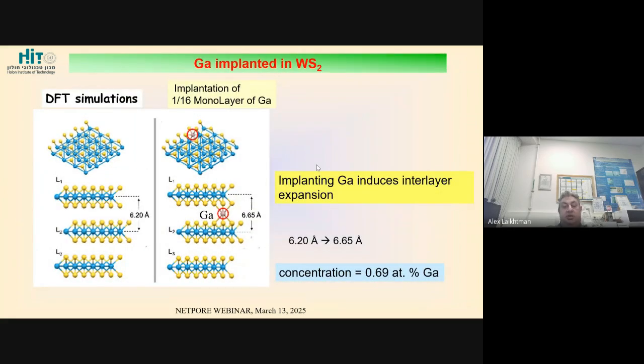And then there are calculations. First of all, if we have just pristine nanotubes which are not treated by hydrogen plasma, then implanting gallium, according to calculation, should induce interlayer expansion from 6.20 to 6.65 angstroms, and then we can produce up to 0.7 atomic percent of gallium, the theoretical limit. So we cannot have any more than this, 0.69 atomic percent.